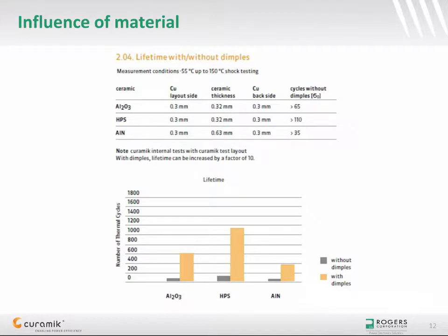We have seen that it is very important to be aware of the test conditions and test criteria used for the assessment of the reliability of the substrate, as they can tremendously impact the test results. Now, we would like to understand which are the possible measures that can be taken to increase the reliability of the substrate. Maybe the most important factor is the selection of the material and particularly the choice of the ceramic. On this slide, you see data taken from Rogers design rules. The high thermally conductive aluminum nitride would be the best choice for the purpose of heat dissipation, but it unfortunately shows poor mechanical properties, and as a consequence, aluminum nitride DBC substrates are prone to fail after few temperature cycles.